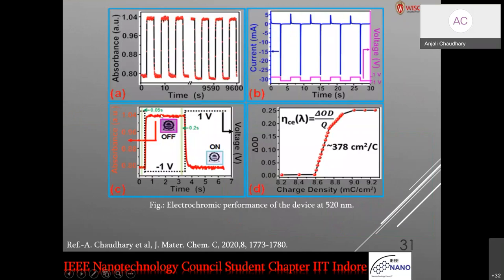It is very good. It took only 0.05 and 0.2 seconds to switch between its magenta and transparent state, and it shows a coloration efficiency of 378 centimeters square per coulomb, and it is quite stable for a long time, nearly 9600 seconds.